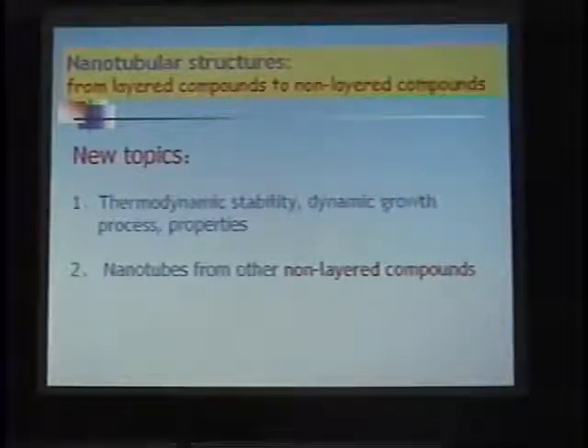This is the discovery of aluminum nitride nanotubes. The importance is that aluminum nitride is not a layered compound. It's a non-layered compound, so the discovery of such nanotubes could extend the nanotube structure from layered compounds to non-layered compounds. And some new topics appear. For example, what's the thermodynamic stability, what's the dynamic growth process, and what are the properties of such a structure or morphology? And second, nanotubes from other non-layered compounds will attract increasing attention. Actually, recently some new nanotube structures from other non-layered compounds have gradually been reported.